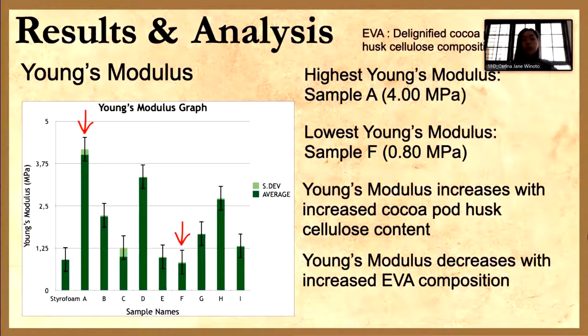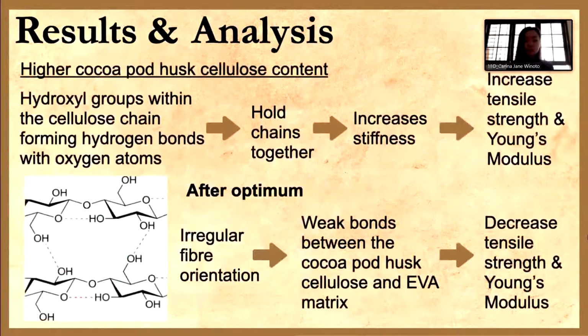Relating to that, we may see within the graph that Young's modulus values increase with increased cocoa pod husk cellulose content, while they decrease with increased EVA composition as well. Such results, especially affected by higher cocoa pod husk cellulose, can be attributed to the fact that hydroxyl groups within the cellulose chain form hydrogen bonds with oxygen atoms, thus holding chains together. This, of course, increases stiffness, thus increasing tensile strength and Young's modulus even further.